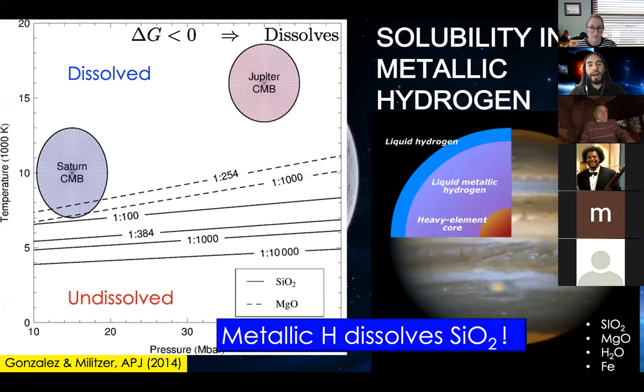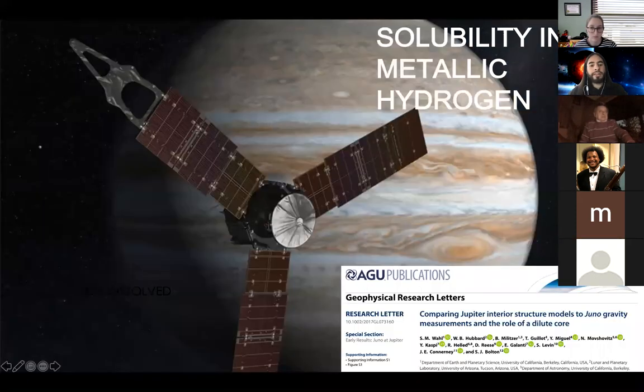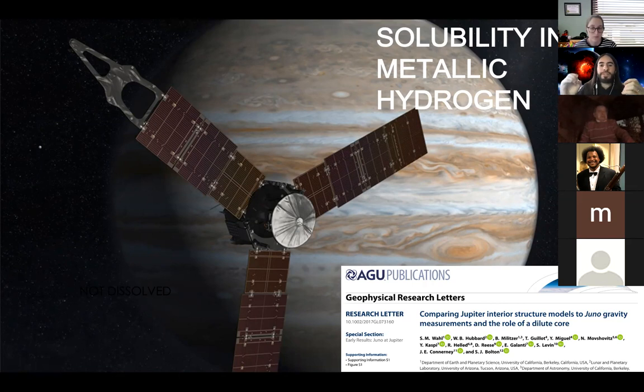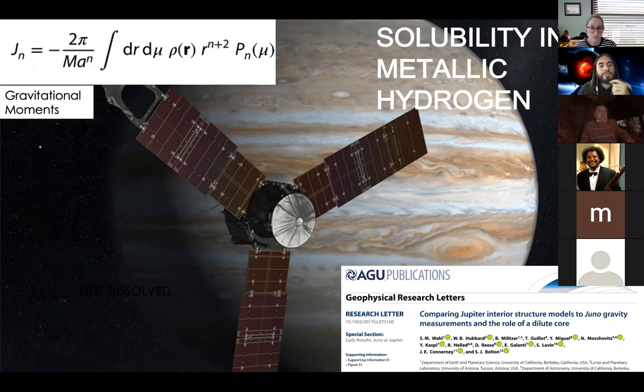So we now think that metallic hydrogen is dissolving in Jupiter's core, but how do we know if this can actually be happening? And it turns out that there's a mission out there called the Juno mission that is orbiting Jupiter and measuring the magnetic field and gravity field to an unprecedented precision. And they're measuring what's called the gravitational moments here, which is nothing but the integral over the density profile of the planet. So if we measure these gravitational moments, it can tell us about what the possible density profiles are at the interior of the planet.